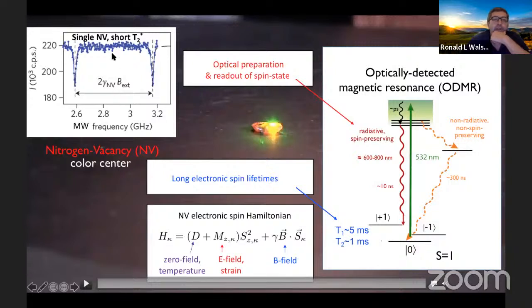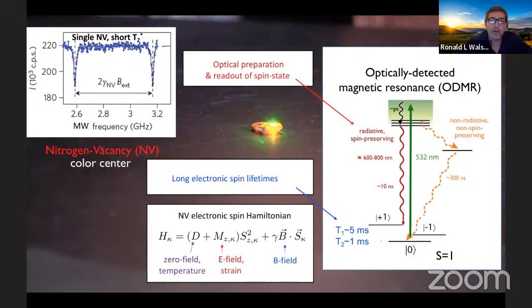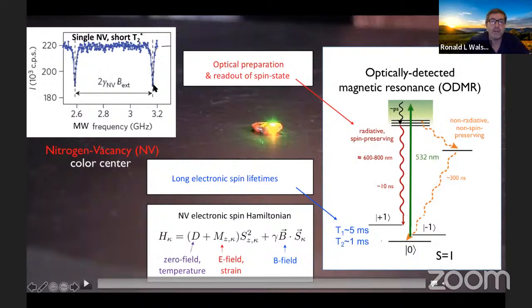Now, if the microwave frequency is in between the transitions, far off resonance of either transition, it's not on resonance with 0 to 1, it's not on resonance with 0 to -1, it's somewhere in between, and you vary the frequency a little bit, you don't see any change in the fluorescence because you're just in ms equals 0, absorbing repeatedly green photons and emitting red photons. You're at the high fluorescence rate that you get with ms equals 0. But once you come onto resonance with either transition, 0 to -1 or 0 to +1, as shown by these sharp dips, there's a competition between the microwaves attempting to drive the NV from 0 to either +1 or -1, which would have a lower average fluorescence rate, and the green laser, which is attempting to pump it back into ms equals 0, where it would have a higher fluorescence rate. So you see a sharp dip right on resonance.